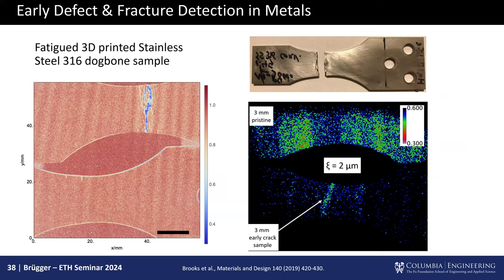The holy grail for this is identifying fractures in the early stage. With neutron grating interferometry, you can detect void nucleation — how a ductile material initiates fracture by creating penny-shaped or round voids, essentially Swiss cheese on the inside, before the material is even considered to be cracked. With NGI patterns tuned to an autocorrelation length of about two micrometers — whatever the material happens to cavitate at — you can begin to detect the initiation point of fractures before that crack mechanically exists. When it comes to optimizing materials, this is incredibly powerful.